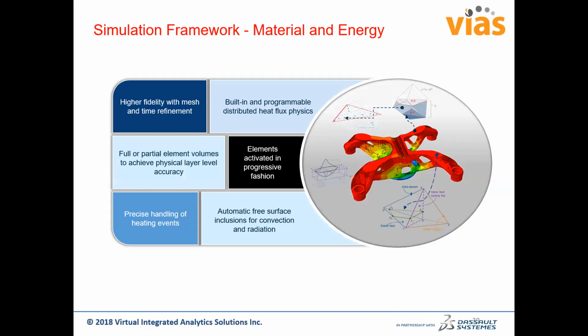One is partial element activation. Now your mesh is sort of like a background mesh, so it doesn't have to follow exactly your interest in time and space. Another thing is you can do a more adaptive simulation. Initially you run your design with a certain coarse mesh, and find out where your high stress regions and large distortions are. Then within that area you can refine your model, with a finer mesh just within those areas to capture the gradient more accurately.